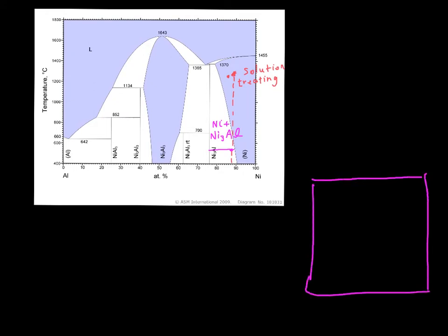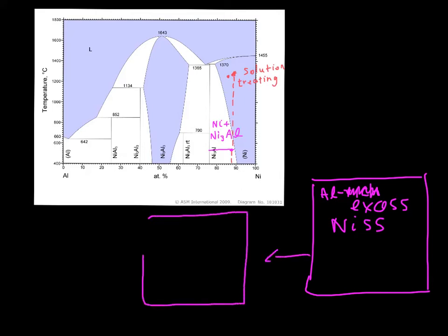So you start out with sort of an aluminum excess. So we have excess aluminum in this nickel solid solution. And what happens then is that you move towards equilibrium where you just have this nickel solid solution, but you can form a number of very small precipitates. So you want a high nucleation rate, but a low growth rate, so lots of tiny precipitates, and these are what then inhibit the motion of the dislocations through this.